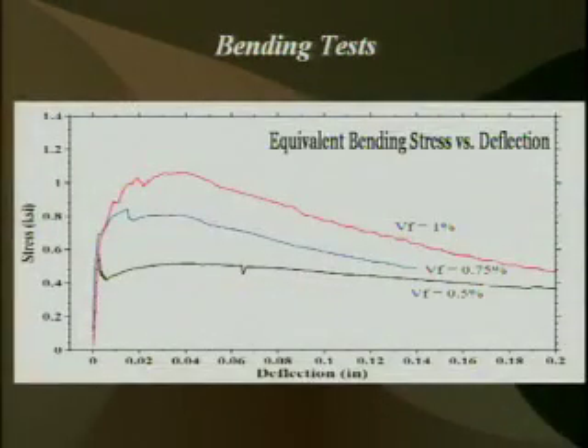As we can see from the results, concrete's post-cracking strength and ductility increases with the amount of steel fibers. The last test that we did were the tension tests, which the results were very similar to the bending test. However, the setup was completely different.